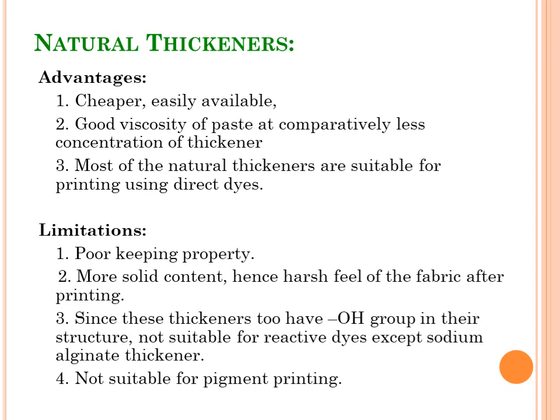Next limitation is that they have more solid content, hence a harsh feel of the fabric after printing. The thickener film will be harsh enough to provide a harsh feel to the fabric, and because of the solid content, there are chances that the thickener film after drying may get broken. Some micro cracks get generated in the film, and from that area the film may get removed, and we may not get the desired levelness of the print effect.